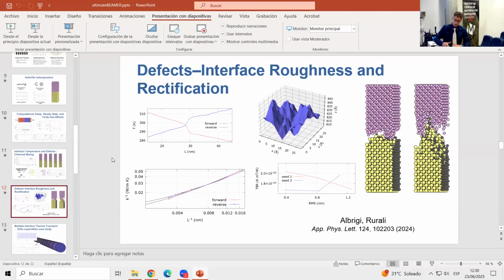Plus, you have to think that when you are increasing the cross section, the cost of the computation increases quadratically, because the number of atoms involved scales quadratically with the cross section. So we did not even try to assess whether our assumptions were right. We were like, okay, with this geometry at this scale, you do not observe any trend. But yeah, I would say that with different materials, different acoustic impedances and so on, it could be.